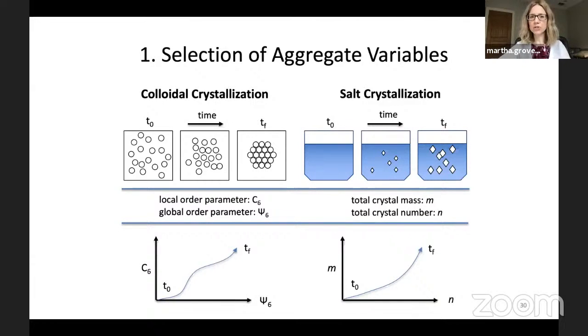Okay, so I just wanted to summarize these two examples and to compare them. We've talked about two case studies, the colloidal crystallization and the salt crystallization. In the case of the colloidal crystallization, we have these micron-sized solid particles, and we're pushing them together with dielectrophoresis to form this crystal of micron-sized particles. And we characterize that system in terms of two aggregate parameters, the local order, C6, and the global order, Psi6. Now, in the case of the salt crystallization, we're actually nucleating and growing crystals in solution. And in that case, we're going to characterize the system in terms of the total mass of crystals, and actually not necessarily the total crystal number, but the total cord count, which can also represent to some extent the total number of crystals.